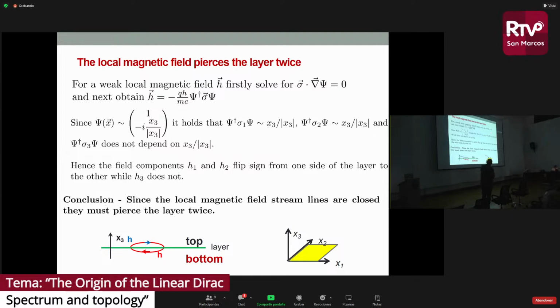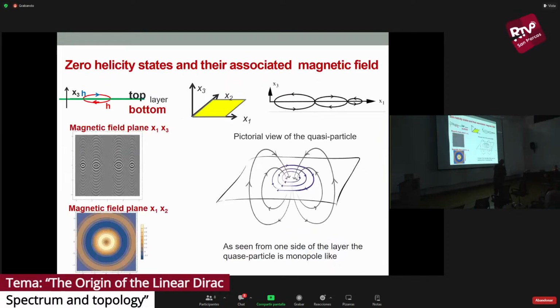If you look at the structure of the wave function, one of the components flips sign as you go from top to bottom. You find that the magnetic field components 1 and 2, parallel to the layer, also flip sign, but not the third component, which means that your magnetic field streamlines are loops like this that go from top to bottom. And this is the key to the topological stability of the states.